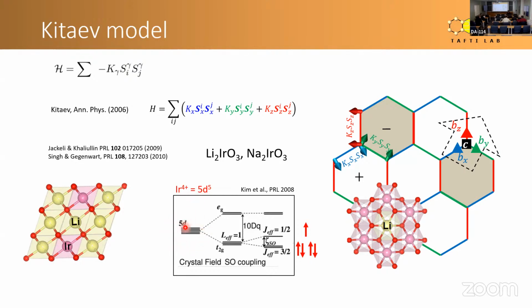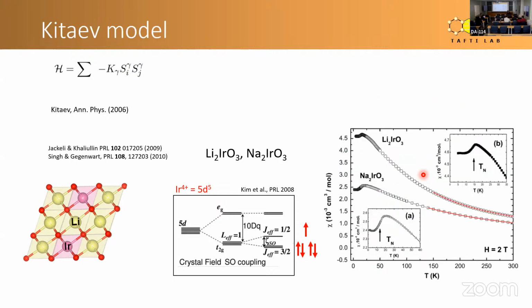Basically, the 5D orbitals under an octahedral crystal field split into T2G and EG manifolds, and then the T2G manifold under spin-orbit coupling splits into J effective 3/2 and 1/2. And then when you put the 5 electrons in those levels, you end up with a single electron in the J effective 1/2. And so this is a J equal 1/2 model on a honeycomb lattice with strong spin-orbit coupling. So those are the initial ingredients for possibly a Kitaev system.